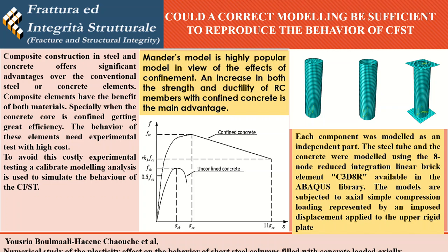To avoid costly experimental testing, we simulated the behavior of CFST using a finite element model. The steel tubes are modeled to simulate different plastic state behaviors: linear elastic-plastic, multilinear hardening elastic-plastic, and the model proposed by Tang, while the concrete core is simulated by Mander's model.